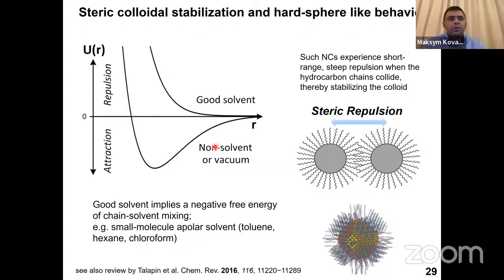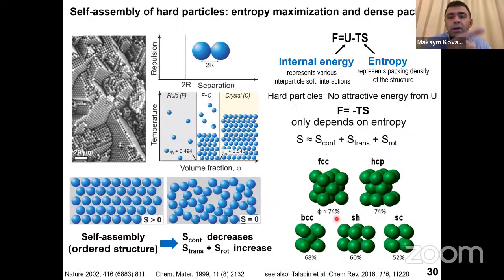How it works is because it works that easily only for the colloids which are so-called sterically stabilized, which is apolar capping ligands like we have for perovskites. And so that the particles experience very short range repulsion, but they rather are non-interacting at the longer distances. So this steep interparticle potential in a good solvent. So this occurs also when you choose the solvent correctly. It has to be apolar small molecule solvent. When you have that case, nanocrystals will undergo spontaneously into self-assembly.